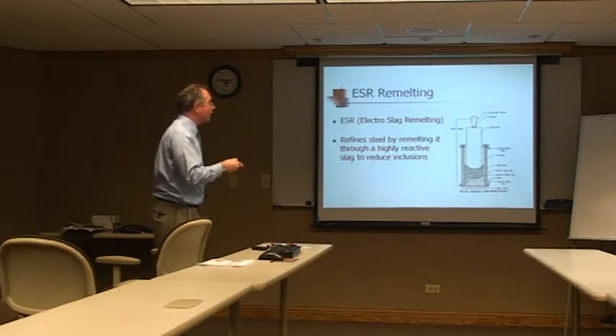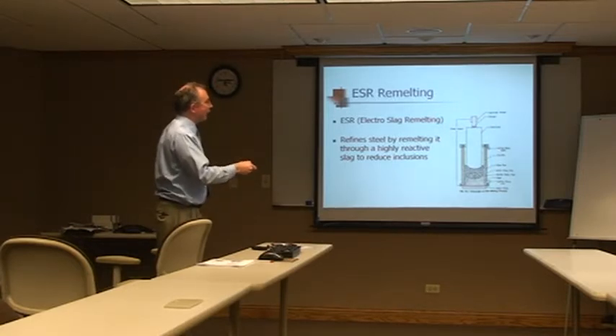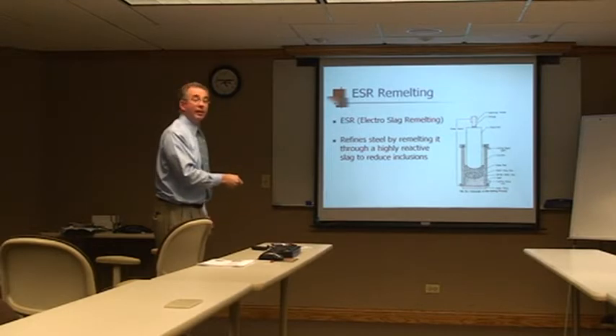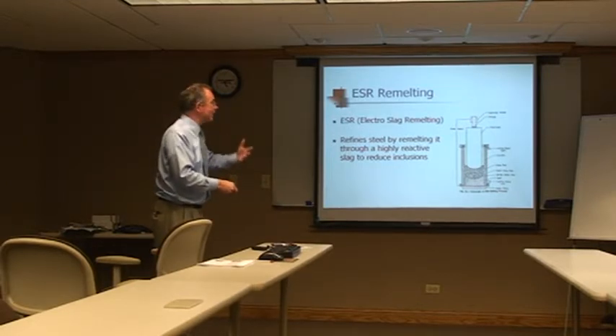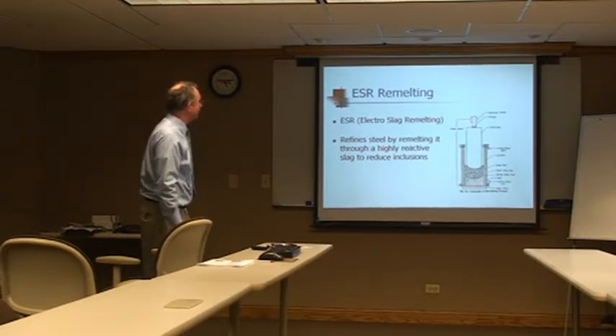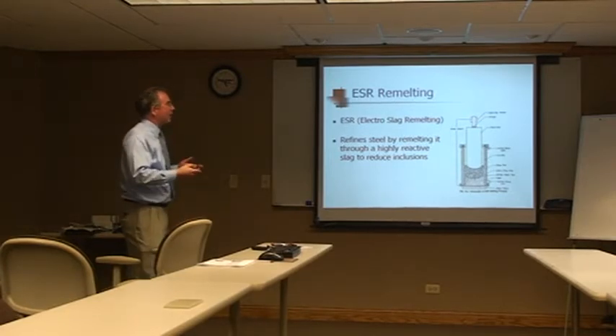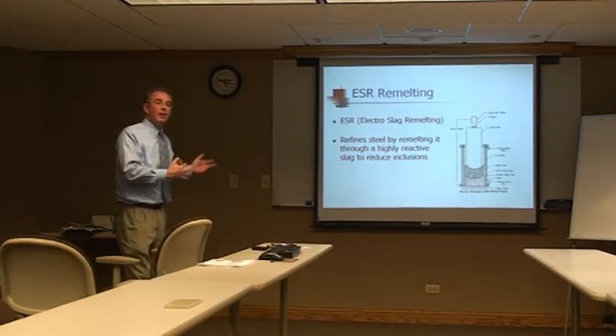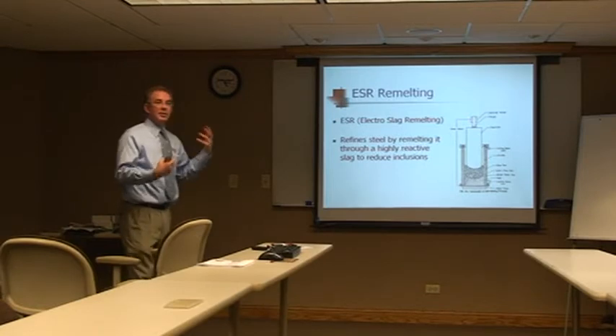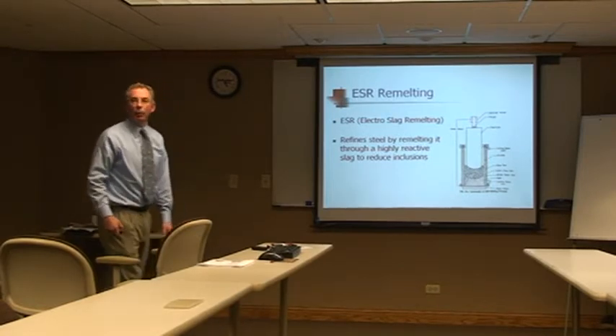Same type of principle. Electrode hung here, electrode holder here, crucible here. Current drives from the source through the electrode, melting the electrode at the tip, and then through the flux, and then they're resolidifying, the ESR ingot below. So the difference between VAR and ESR, VAR is under a vacuum, ESR uses a slag for improving the quality.